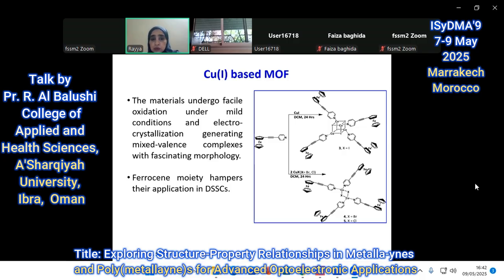The materials undergo facile oxidation under mild conditions, and we found that by changing only the copper salt, from copper iodide to copper bromide and copper chloride, we have different morphologies. For example, with copper iodide we have this cubic morphology, while with copper chloride and bromide we got the dendritic structures. The problem we faced with these materials is that the presence of ferrocene hampered the processing of these materials and their applications, especially in solar cells, because the materials had low solubility.